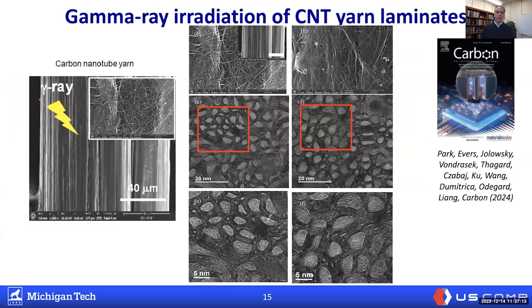All right, now I had hinted earlier what we did next. So this paper that just recently came out in Carbon, we actually took these composite materials, we irradiated them with gamma rays. So straight out of Marvel Comics, we shoot these things full of gamma rays to hope to make them stronger. And so what you could see right here is a typical side view of a carbon nanotube yarn. And what you see here is a combination of SEM and TEM images. Now, what you get out of this comparison, so the left-hand side is before irradiation, the right-hand side is after irradiation.